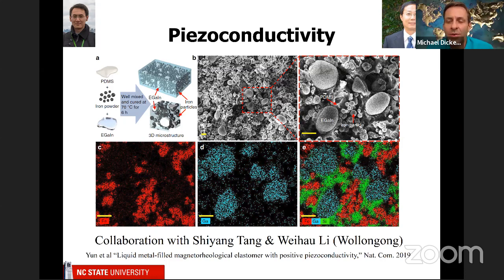I should have said this up front: I didn't really contribute all that much to this, and I'm just showing this to this community because I think the results are quite interesting. So in this work, you take this composite material and you can measure the resistance. And what you find is that the conductivity increases with strain. And I'm emphasizing that because it's very unusual.